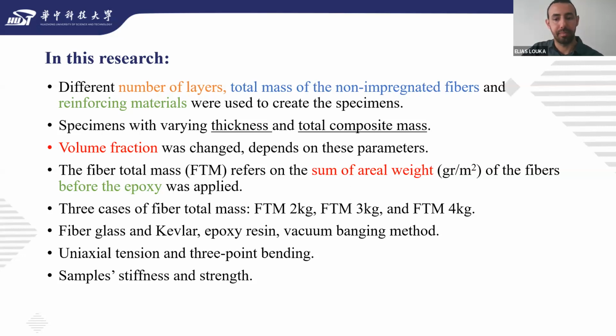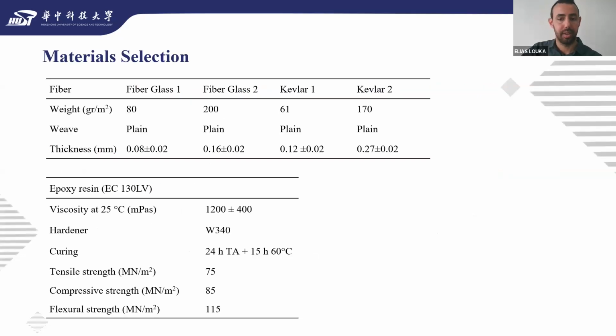Now let's move to the material selection. The composite were prepared by using 2 types of fiberglass and 2 types of Kevlar with different areal weight, grams per meter square. A woven reinforcement with plain weaving at 0 and 90 was used. You can see their thickness in the first table. Epoxy resin was used as the matrix material. We will find some of its characteristics in the second table, like viscosity, hardener, curing time, tensile, compressive, and flexural strength.